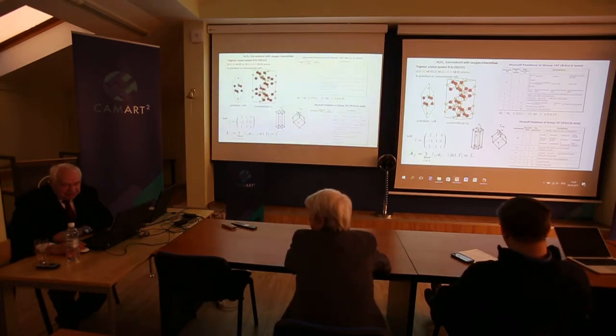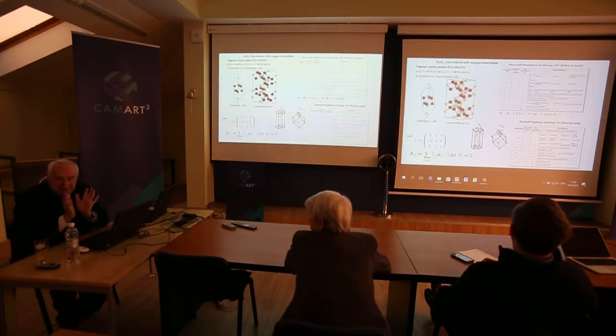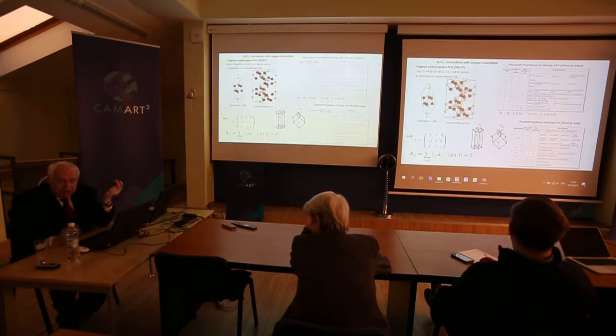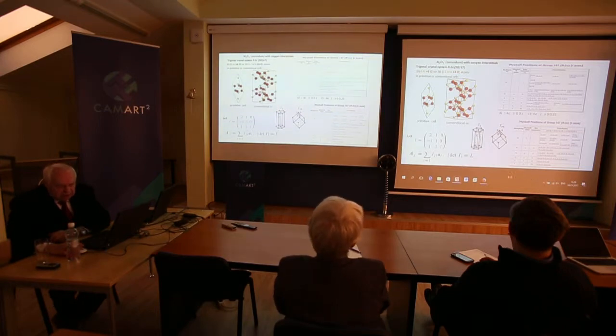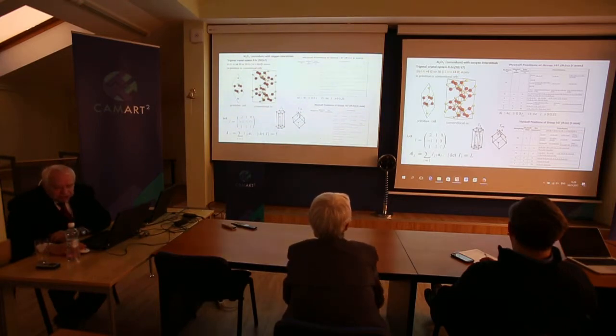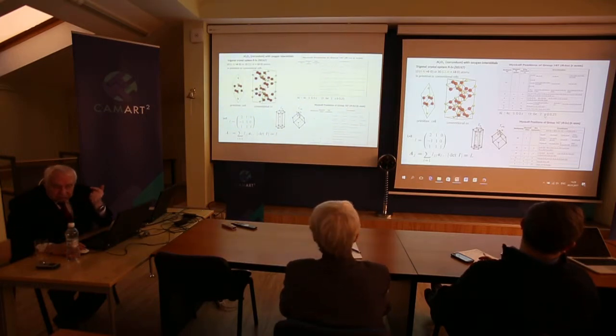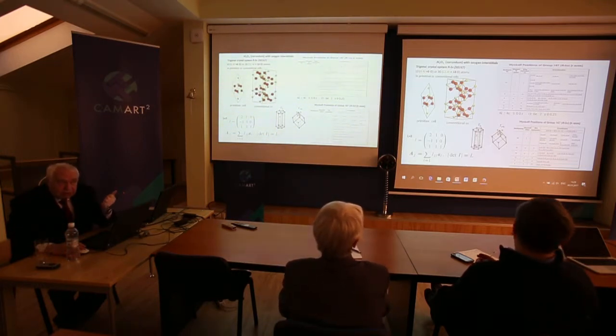The rhombohedral lattice is defined by translation vectors, the lengths of all of them are equal, so 1, and the angle between them, not 90, not 120, not 60, second. So 2 parameters for the lattice. And aluminium occupies a position with 1 parameter, 3, and oxygen with another parameter, 4. So the corundum structure needs 4 parameters.